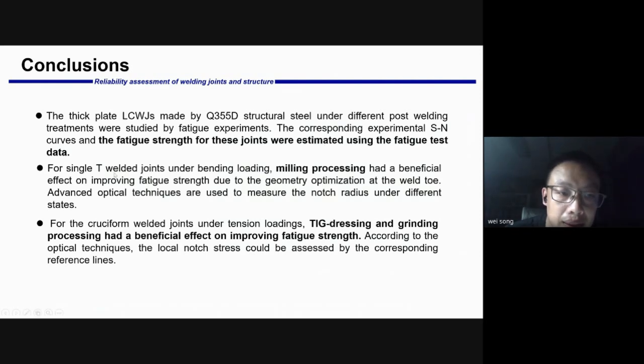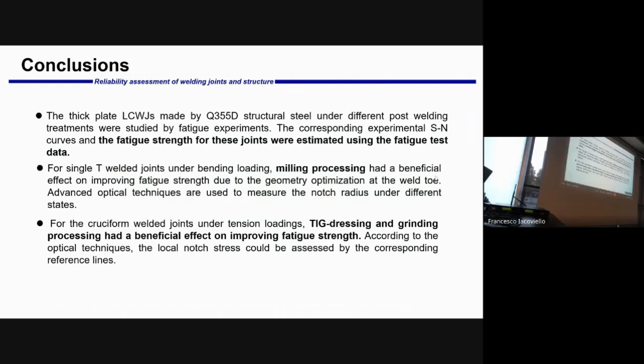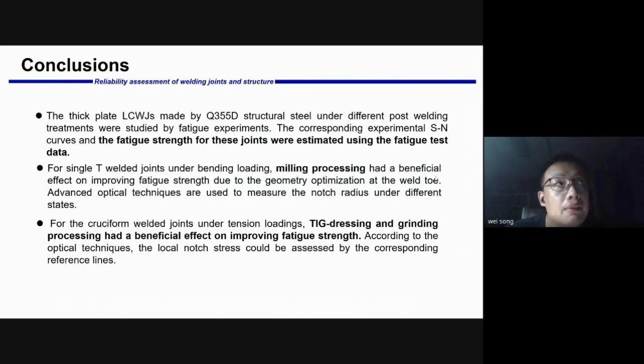Second, for the T welded joint under bending loading, milling processing has a beneficial effect on improving fatigue strength due to the geometry optimization of the weld toe. The third is about the cruciform welded joint. Under tension loading, the TIG dressing and the grinding processing have a beneficial effect on improving fatigue strength. I want to note that this result is just the fatigue test data, and in the next step we should analyze the fatigue reliability under different fatigue approaches, considering the weld toe and the scatter of the weld notch radius.